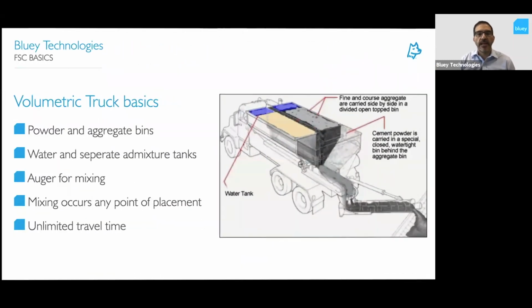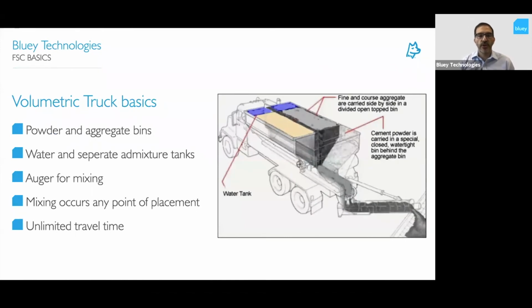So looking at some of the application systems, I mentioned volumetric trucks earlier, and these have changed the way we apply fast set products, but in themselves, they've also changed, particularly over the last 5 years or so. So what it is you have powder and aggregate bins, which are separate. So you have your cement powder, and your sand and aggregates, which are put into separate bins. They drop down into an auger, and then that's mixed off a conveyor belt through that auger, and the mixing actually occurs at the point of placement. So we're not adding water to our powder until we're actually ready to place the concrete. And what that means is you have unlimited travel time with the products.